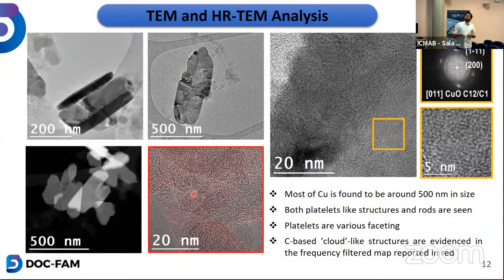We also have done some TEM and HRTEM analysis, thanks to Jordi Arbiol from ICN2. We have got some unexpected results. Actually, we wanted to see how the nanoparticles look. We have seen different types of nanoparticles in our samples, like rods, cuboids, and platelet-like structures. Most of them are around 500 nanometers on average. I don't know if we can call them nanoparticles, because they're quite big in size. But the good thing is they're good for my type of reaction.